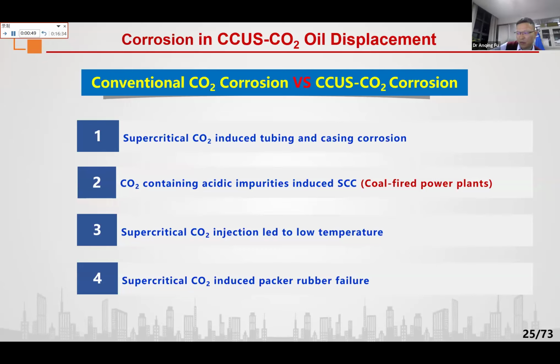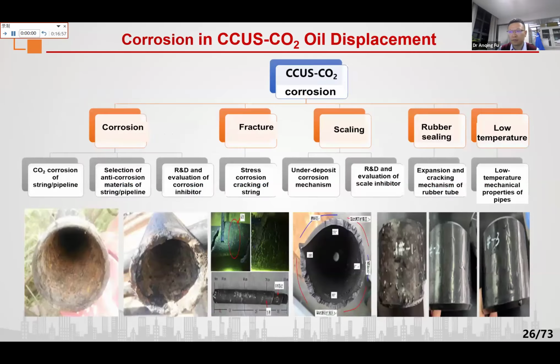Actually, we can find this kind of scenario in our lab. If you pressurize CO2 into our autoclave, you can see there is some ice. The temperature quickly goes down due to the CO2 injection. The last one is supercritical CO2 induced packer rubber failure. Based on our research, supercritical CO2 with multiple impurities can cause, first, corrosion. The second one is SCC, as I mentioned earlier, stress corrosion cracking and scaling, since the supercritical CO2 carries a lot of ions, which can lead to scaling. The third one is packer rubber sealing failure, and the last one is low temperature fracture.